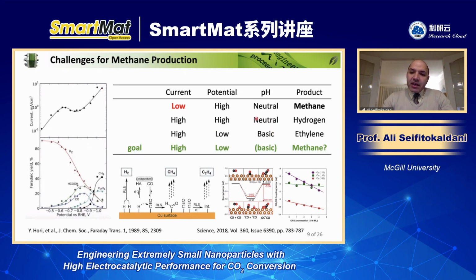But then if we move to a much higher voltage to further increase the current, we realize that hydrogen picks up and becomes the dominant product. So you cannot simply increase the potential and increase the current in a neutral environment, because then hydrogen becomes the dominant product. But then people use basic environment, and we have a paper here, you can look into that.